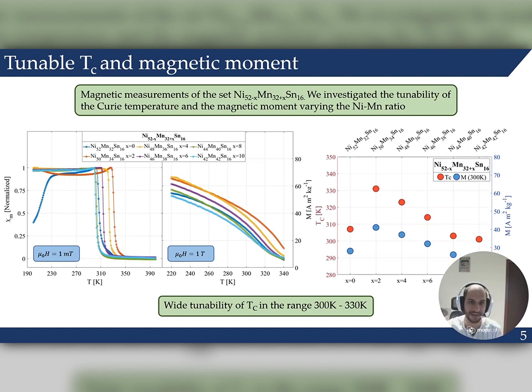Firstly, we synthesized a set of nickel-manganese-tin samples by varying the ratio between nickel and manganese, and we conducted some magnetic measurements. For example, on the left of the first figure are shown some susceptibility measures over temperature conducted with a TMA, thermomagnetic analysis, that is basically a susceptometer with an applied field of 1 millitesla. While on the right of the same figure are reported some isofield curves measured with an extraction magnetometer with an applied field of 1 Tesla. Then on the right of the slide are reported the Curie temperatures extracted from the TMA measurement and the values of the magnetic moment at 300 Kelvin.